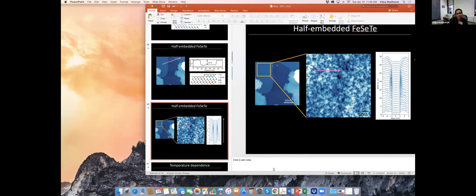I mean, there's a reason. I can tell you the reason. Yeah, go ahead. The reason is the way we grow it. It's iron deficient in some ways. It's a clever technique, actually. We didn't invent this. You put iron on top of bismuth telluride, just iron, and you anneal it in a selenium atmosphere. And so all the iron that exists on top binds to either selenium or tellurium. That's why you end up with no excess iron.